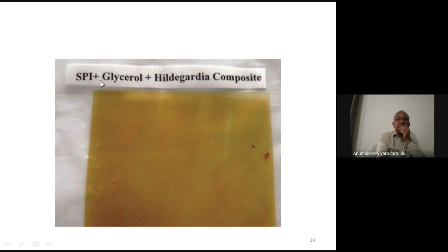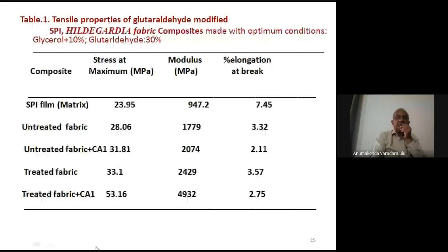So this is a film we made. This is a composite film, SPI, glycerol plus Hildegardia. Hildegardia is a uniaxial fabric that is available, and the Telugu name is Gali Buduga. The seed will be like an air balloon. So we studied its mechanical properties. The SPI matrix is having only around 24 megapascals, but when we have added this fabric and coupling agent, its strength has gone more than doubled, 53.16.